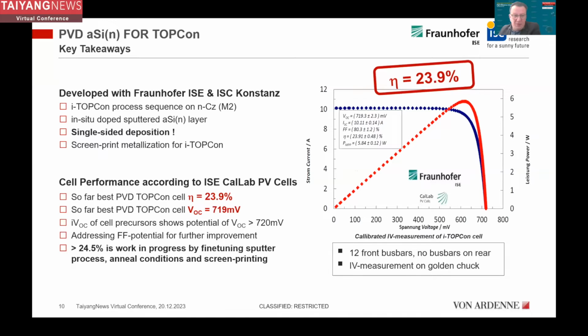For sure, if you compare to the records you saw during these days as well, these are not the records, but these are the same efficiency level as the Fraunhofer and ISC have achieved also with other LPCVD or PECVD approaches. However, we see a lot of potential to increase the efficiency, especially when it comes to the fill factor, which is only at 80%. And this work is in progress to do the fine-tuning of the sputter process, but also the emitter profile and the annealing conditions and screen printing design.